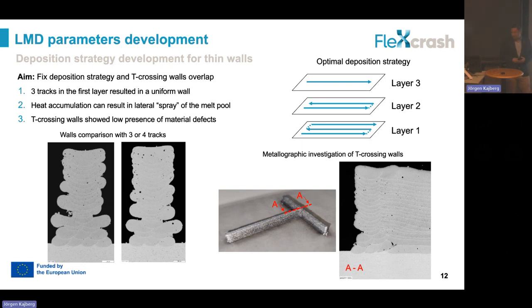In order to be able in the future to design not only single walls, but also crossing walls, where maybe from the simulation we will see that this type of crossing walls can achieve a higher energy absorption during the crash of our components, we also have to optimize the deposition strategy. As you can see, in this case, we have formation of significantly bigger pores in the crossing points. However, at a higher level, we didn't have this type of defects. These defects, for sure, are characteristic of the process itself, and we have to consider them during the testing, also to have the material properties that we will use to simulate the shape of the final reinforcement structures.